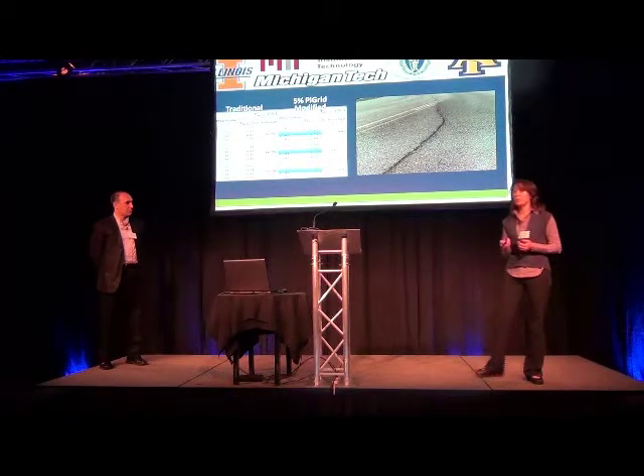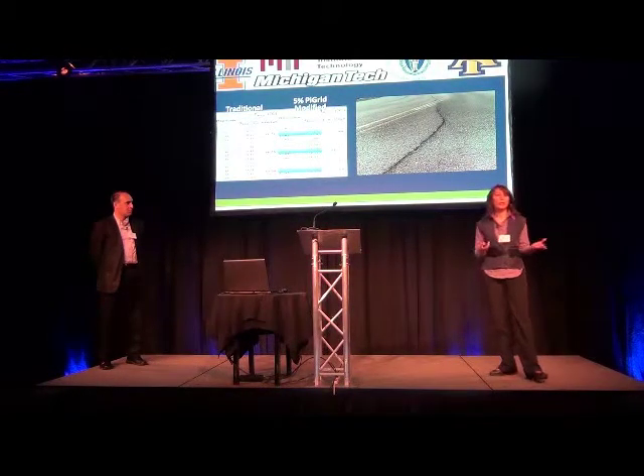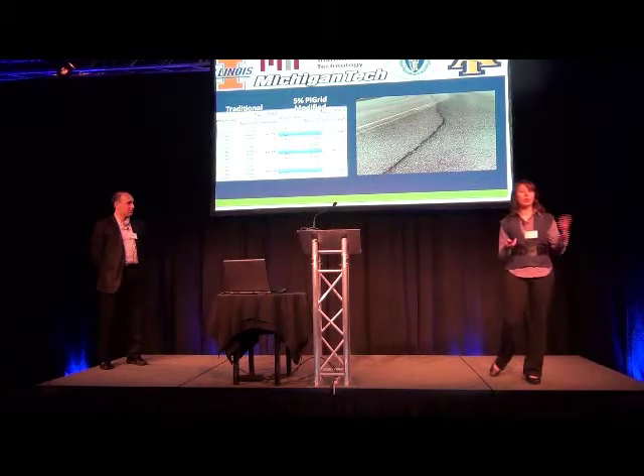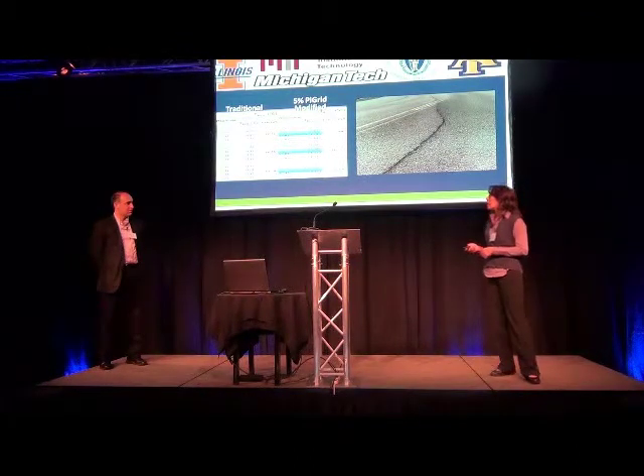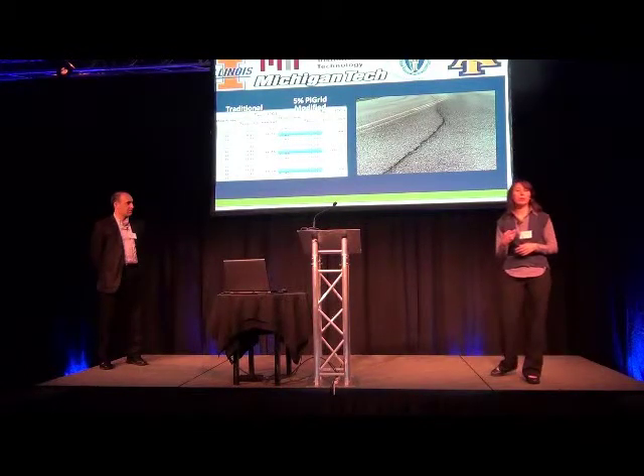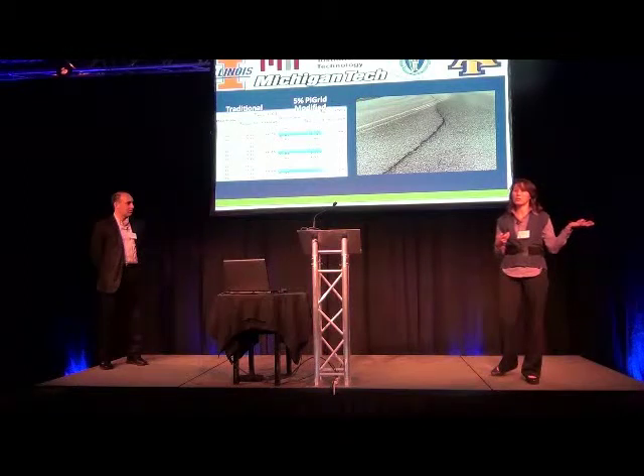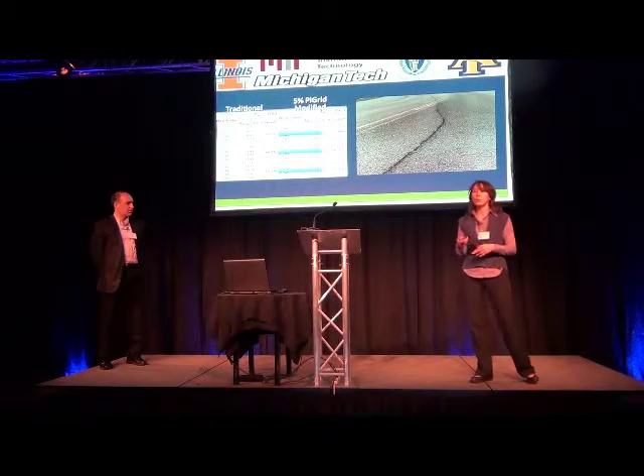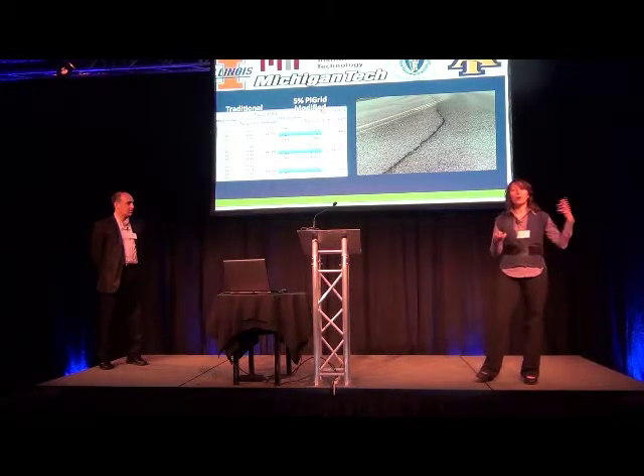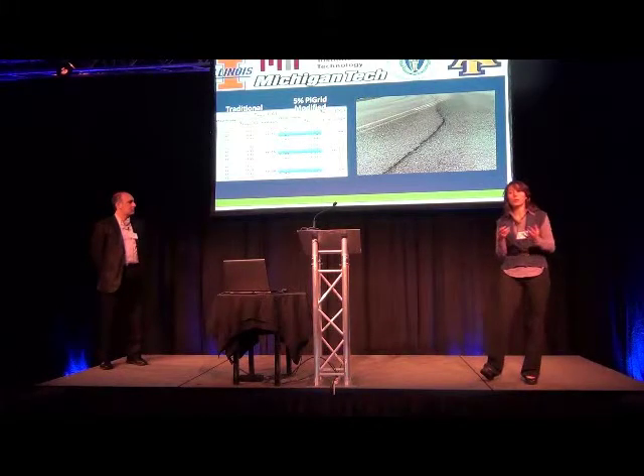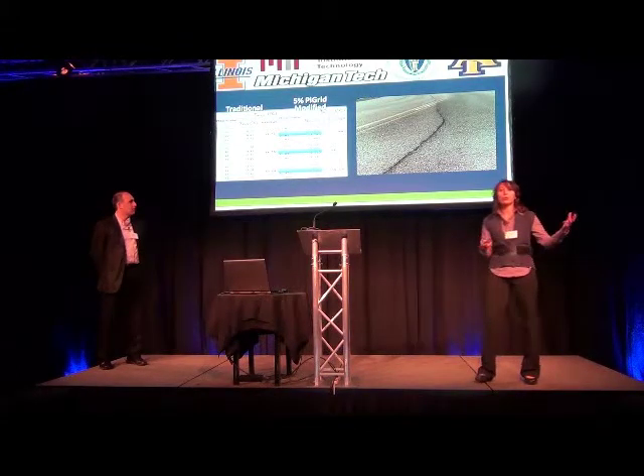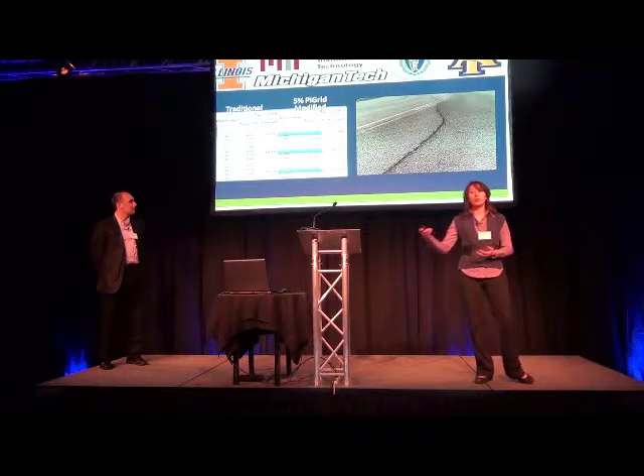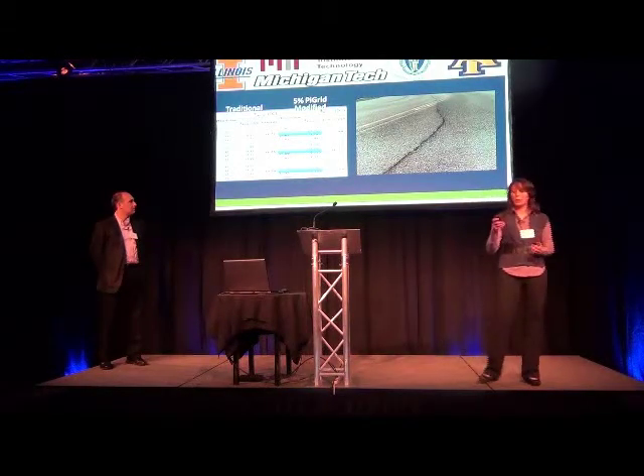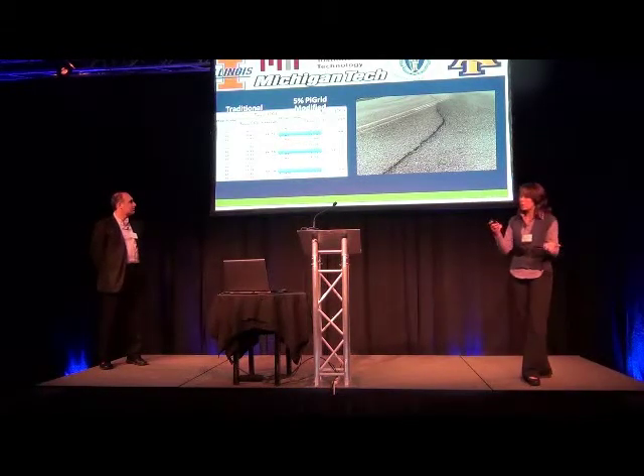Right now, most of the Departments of Transportation are pushing the envelope of using recycled material in new construction. And with this material, we can push the envelope further. Like I know in North Carolina, we are up to 30%, Texas pushing the envelope to 40–45%. And the limit on how far you can use the recycled material is the limit on the cracking resistance. The more you use recycled material, the harder it is to control the cracking and keep the quality. So there's a compromise, it's a trade-off in a way.